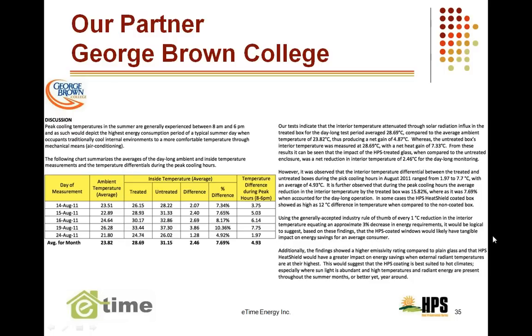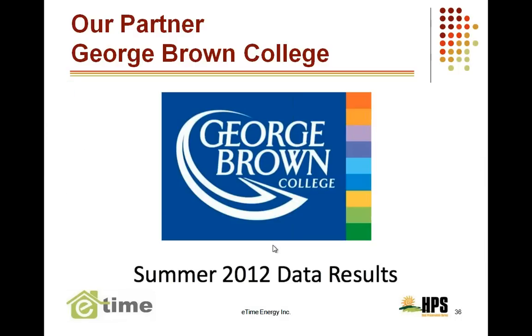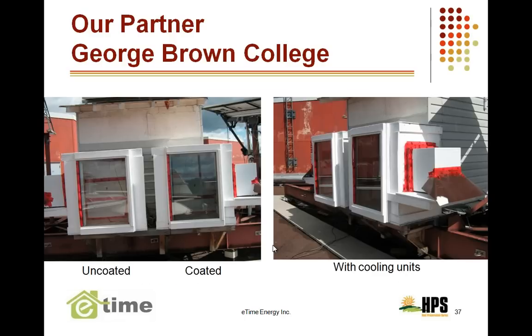The peak load, which is the far right column, temperature difference, and this is between 8 and 6, you had almost a 5-degree difference, which is 15%. So between the two elements, we're well within the range of that 10% marker that we were looking at. So this is a success. They further tested this summer, and in the test this summer, we set up 2 booths on two separate boxes on the roof that both had refrigeration.